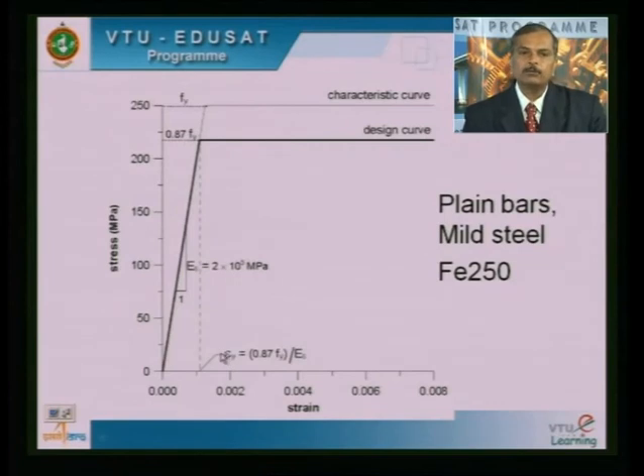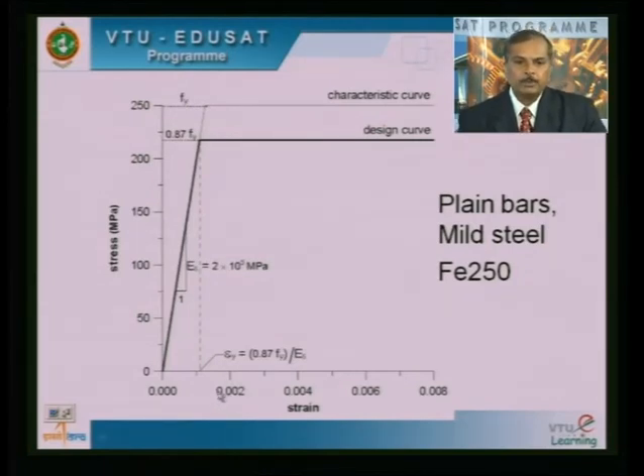And in the assumption we have just now seen that the maximum strain in concrete is 0.2%, that is 0.002. So when the column is subjected to a strain of 0.002, concrete is also subjected to 0.002, and at the same time steel also will have a strain of 0.002. So corresponding to this 0.2% of strain in the column, what is the stress in the concrete that has been identified earlier? Then what is the stress in the steel? The stress in the steel at this particular point corresponds to 0.87 times fy, provided you are using plain bars or the mild steel having Fe 250.